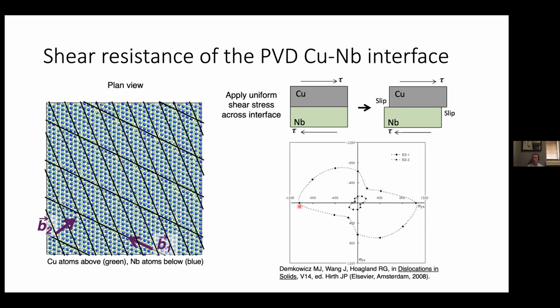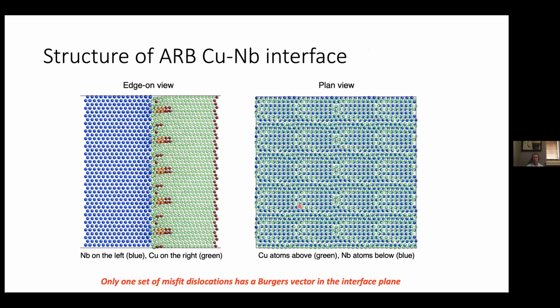are configured, right? Here's the other interface that I was telling you about. This is the ARB interface, so the accumulative roll bonding interface. Again, here's the edge-on view, and here's the top-down view. This interface is also made up of dislocations. If you look carefully, you can actually see in this edge-on view that there are locations where you've got 3 planes coming in from the left, joining with 4 planes on the right. So that tells you by itself that there's got to be an edge dislocation somewhere in there, right? And indeed, if you look through, there's a bunch of locations where there's an edge dislocation.